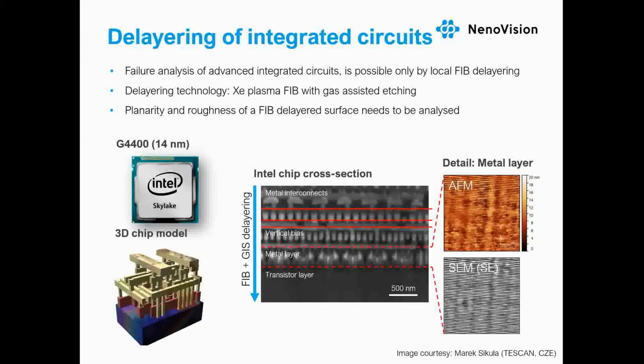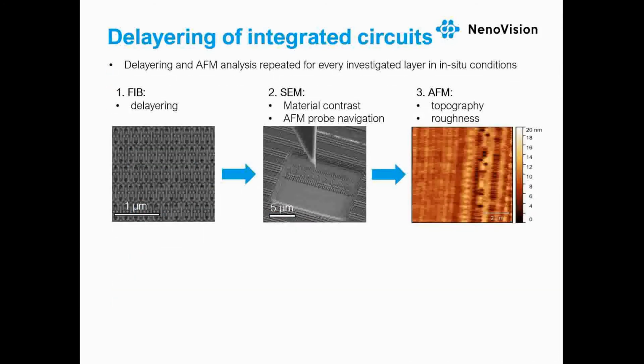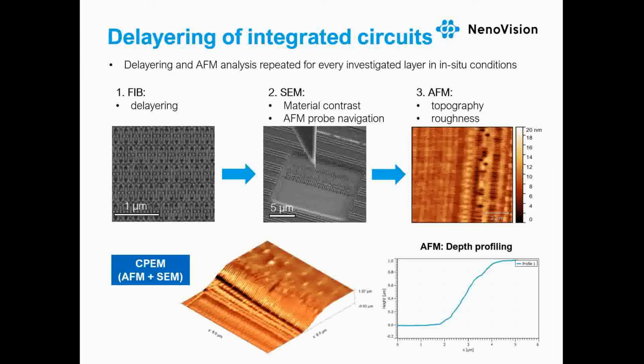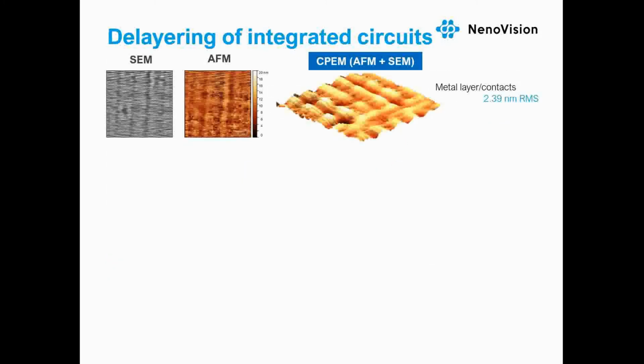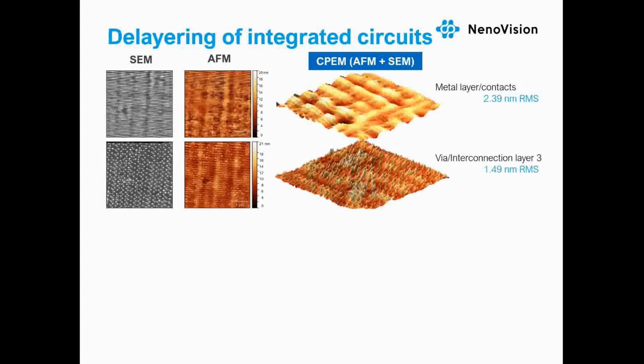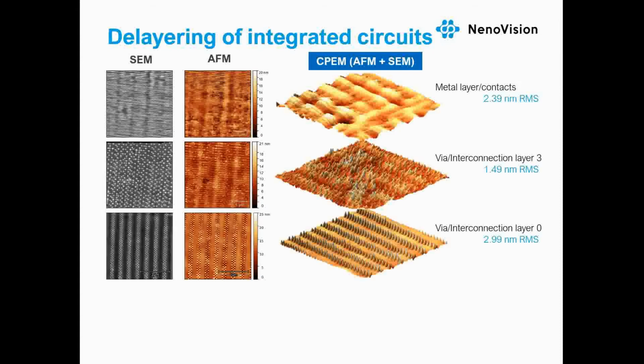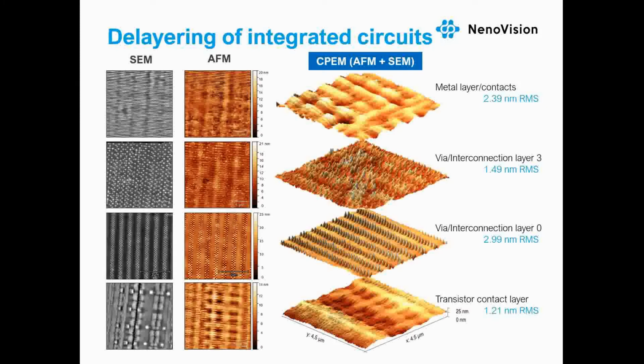The integrated circuit was FIB milled layer by layer, and each layer was scanned by LiteScope and the SEM. Subsequently, AFM and SEM data were correlated by the CPEM technology for better data interpretation. Complete analysis, including depth profiling and roughness measurement, was performed in in-situ conditions to prevent surface contamination and oxidation. The combination of three techniques, focused ion beam, SEM and AFM, was used for complex analysis of the integrated circuit. The SEM was used to control the delayering process, to precisely navigate the AFM probe, and to provide the material contrast. AFM provided information about the planarity and surface roughness of each layer.